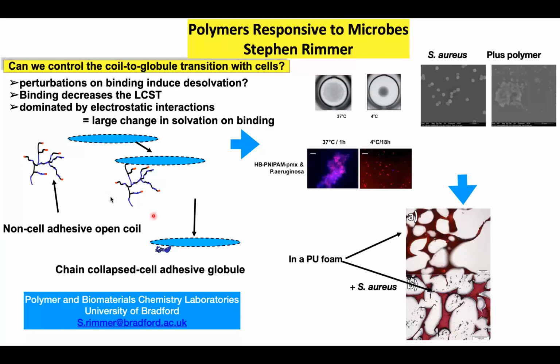Now, really briefly, we take a branched water-soluble polymer with specific ligands attached to the chain ends. These polymers bind to specific targets on our microbes. When they bind, importantly, they go through a desolvation. So segments, and you look at the black bits of my cartoon here, lose water, desolvate, in a process that is really very similar to protein refolding.